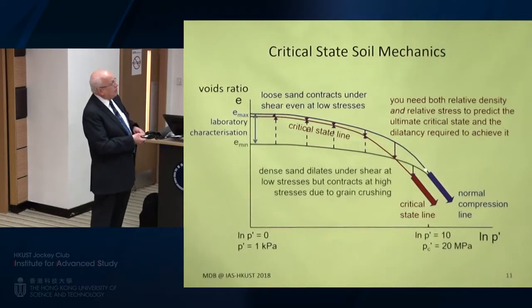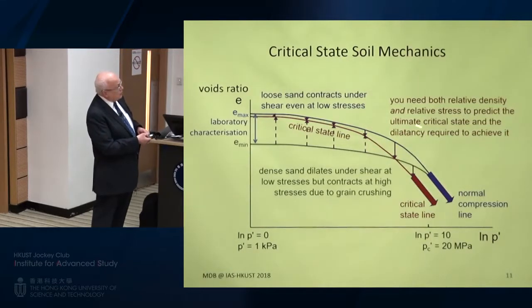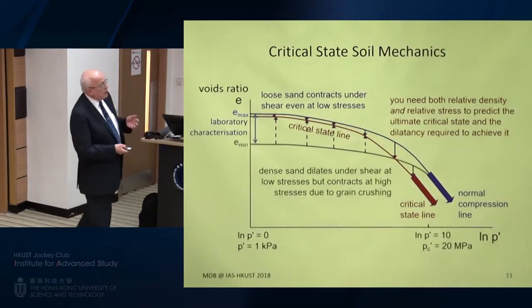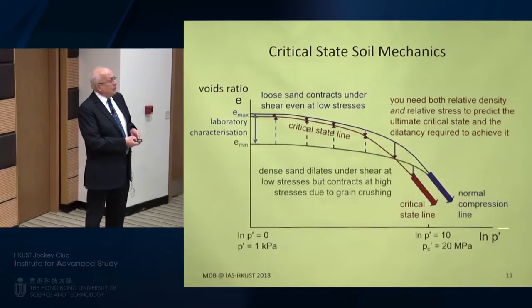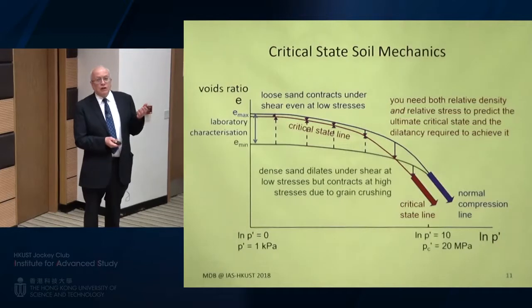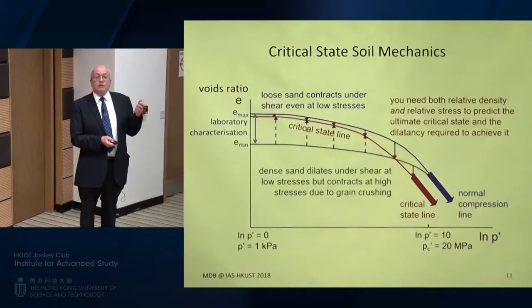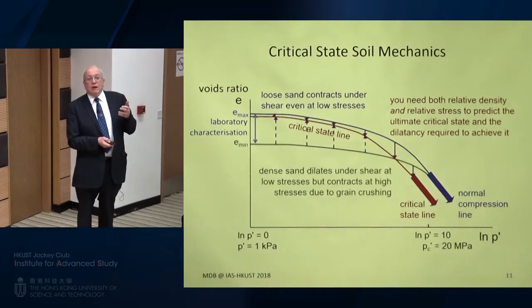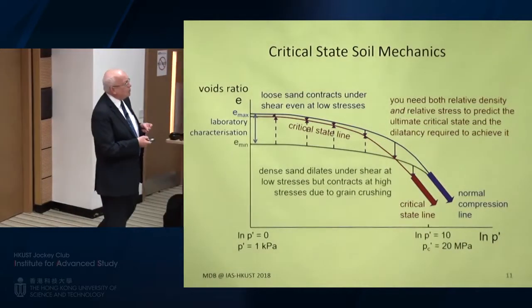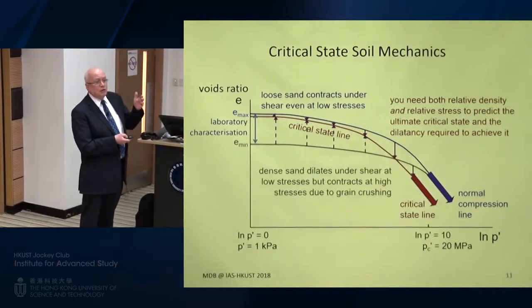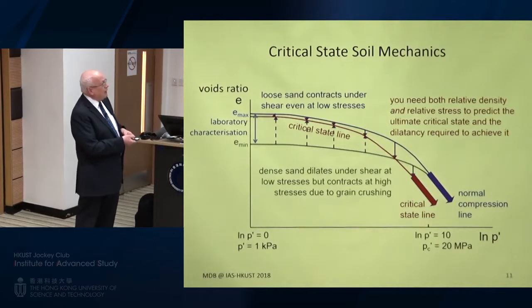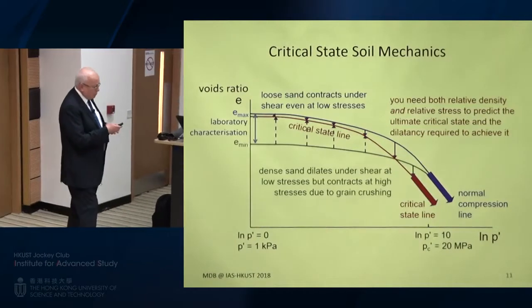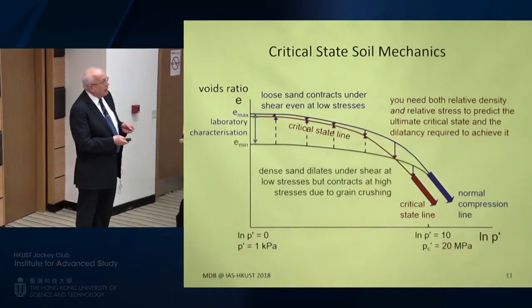it has become clear, at least to me, that the plastic strains, the permanent settlements, the permanent void ratio reductions caused by enhanced stresses are due to breakage. And the linearity of the normal compression line is a function of some clever mathematics, if you want to look at it that way, that Glenn McDowell did, partly when he was at Cambridge and much more now he's a professor at Nottingham, due to the breakage not only of grains but of the fragments that are broken grains. And so you can end up sure that these are examples of fractal compression and breakage of equal probability of breaking any element.